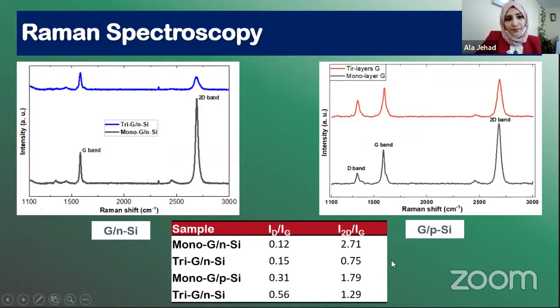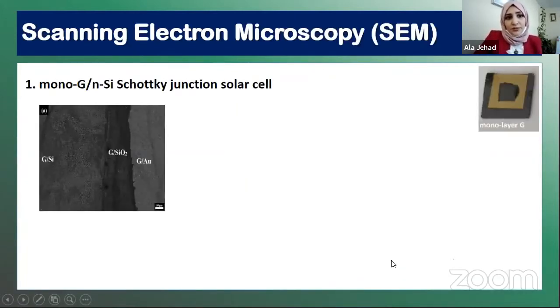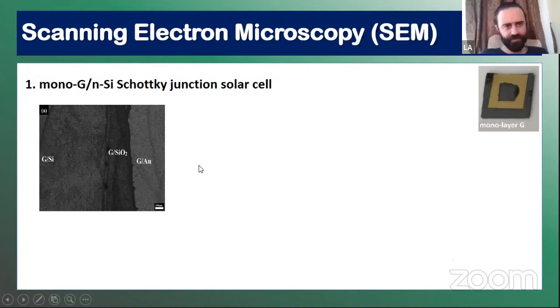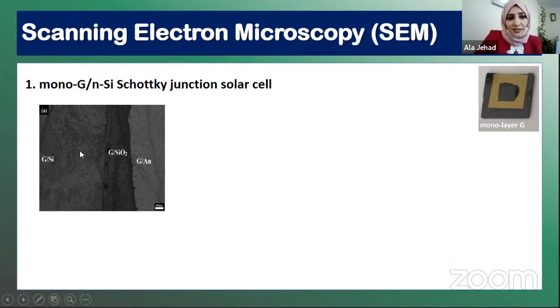The second result was for scanning electron microscopy. Here we can see from the image for SEM, we can distinguish 3 different colors. Here we have the gold, which is this part. And here we have graphene on silicon dioxide, and here the active area, graphene on the silicon.